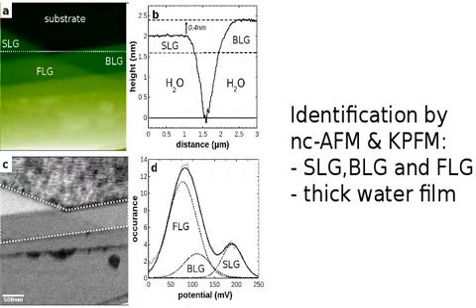The corresponding topography, in A, shows a thick water layer underneath the graphene. To understand this water layer, we have to go back to the preparation method.